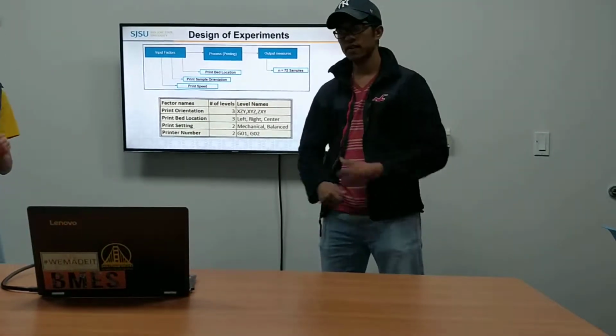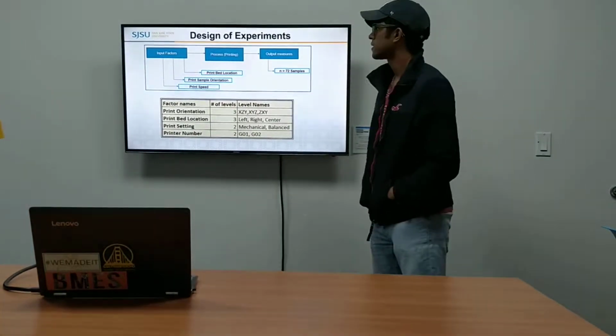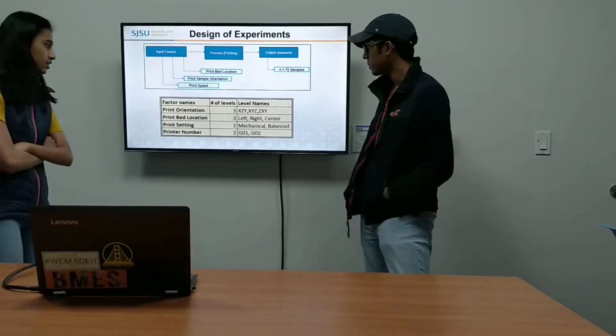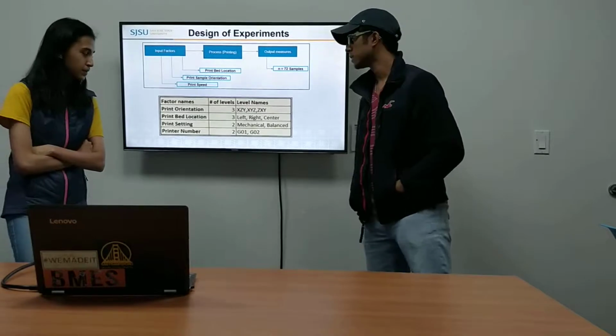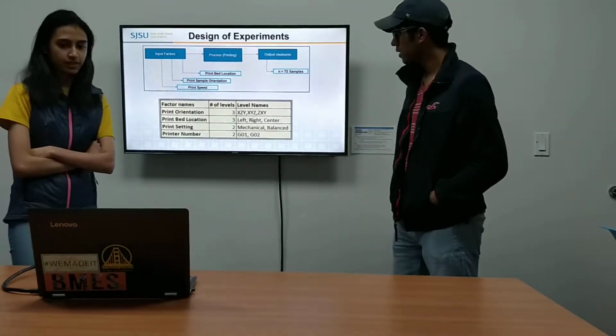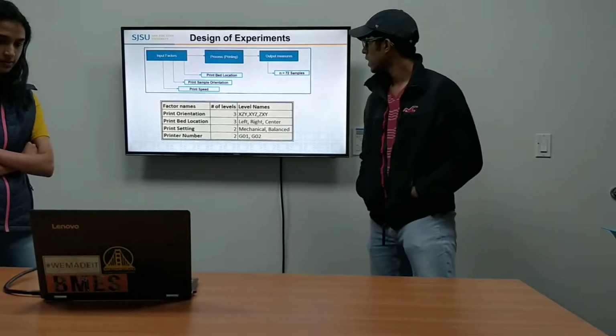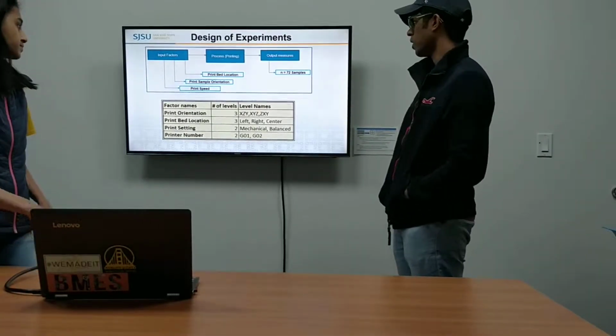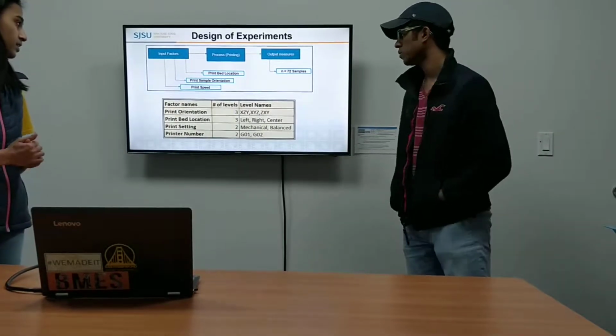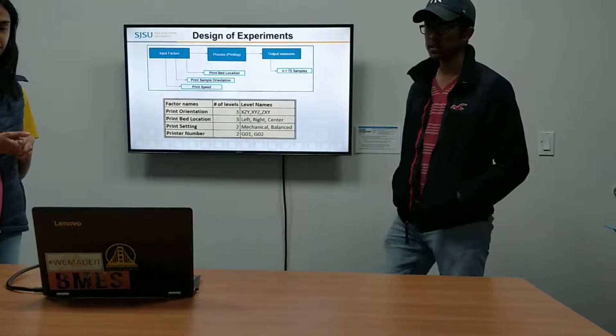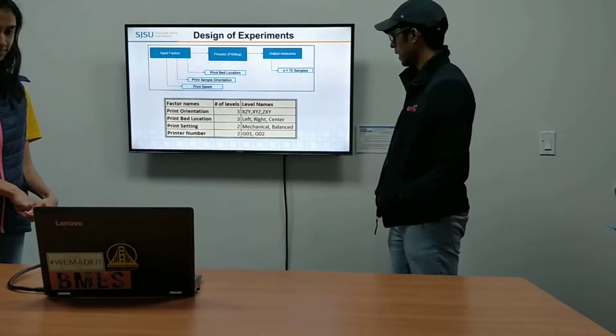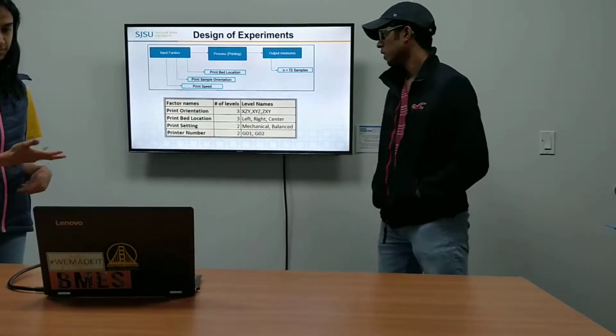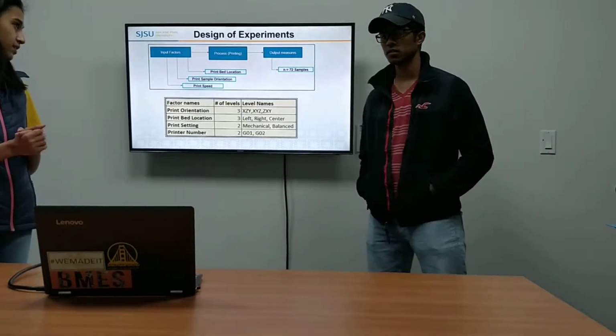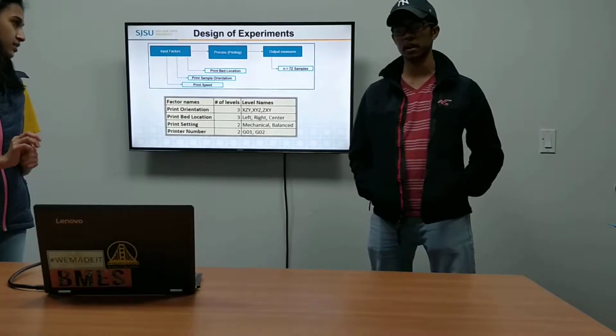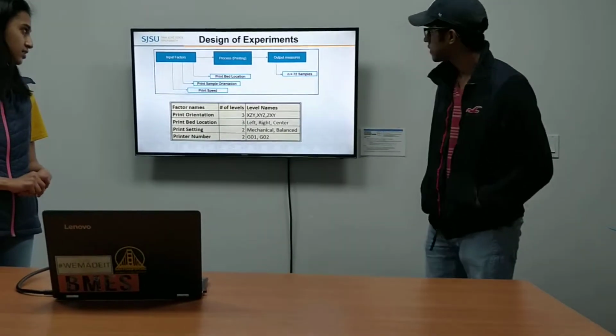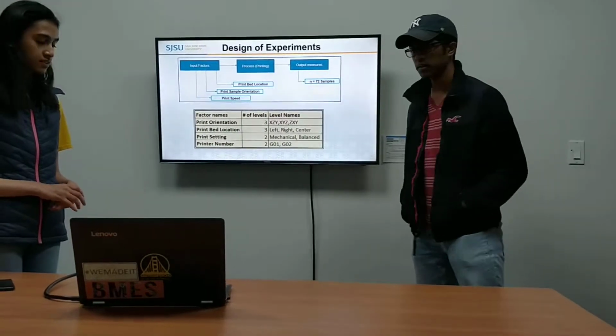So I'll be talking about the design of experiments. For our input factors, we have 3 parameters that we're considering: print bed location, print sample orientation, print speed, and the 4th is print number. It's the different printers that we're using for our project. The different numbers of levels for them are: print orientation has 3 different orientations, XZY, XYZ, ZXY. Print bed location is the location where the specimens are built, and that's just ordered as left, right, and center. And for print setting, there are 2 settings that we'll be using for all of our specimens, and those are mechanical and balanced. In total, we'll be printing 72 samples for our project that will account for all the parameters that I just listed.